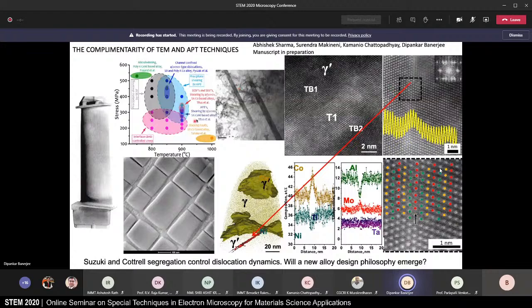And what this work did was to define creep properties of these alloys. And so you see a comparison of stress, temperature, and the microscopic mechanisms that are associated with creep of these materials. So you have, for example, a situation where dislocations are just confined to these gamma channels of this two-phase FCC matrix and Ni3Al precipitate structure. So a stress-temperature combination in which dislocations are restricted to these channels. A stress-temperature combination at higher stresses in which the Ni3Al is sheared.